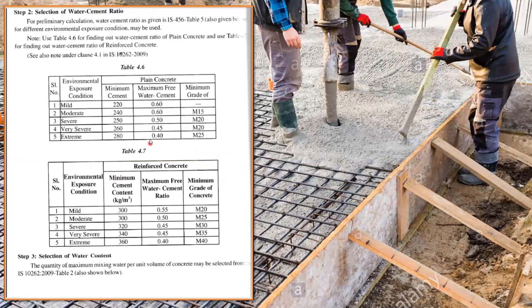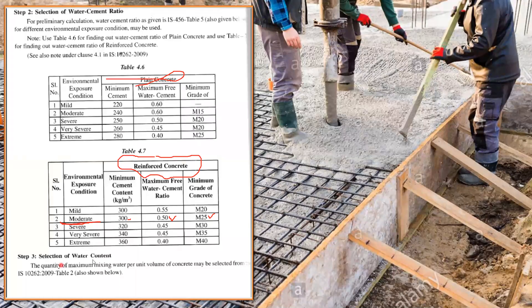Correcting the earlier reference — for RCC we use the relevant table. Taking a moderate exposure condition: the minimum grade of concrete is M25, maximum water-cement ratio is 0.50, and minimum cement content is 300 kg per cubic meter. You must not go beyond 0.50 water-cement ratio for moderate exposure with M25 grade concrete.